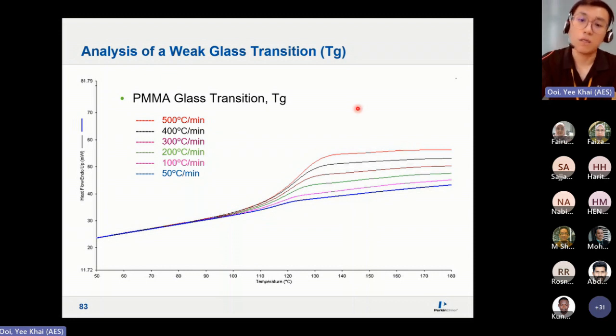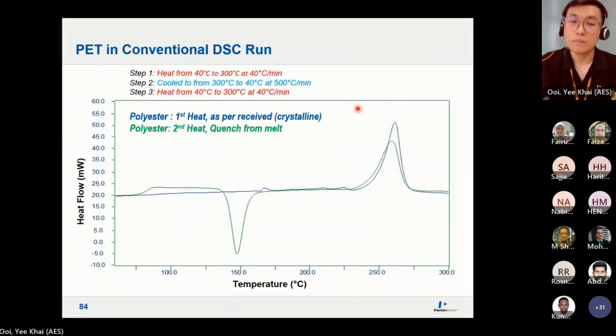This is the Tg for the PMMA. Then you can use this for simulating quench cooling from the melt. So this is a polyester material. It is also a semi-crystalline material. So first heat, semi-crystalline, you see, we heat it up at 40 degrees C per minute. Heat it up. So no recrystallization because the material is crystalline to begin with.